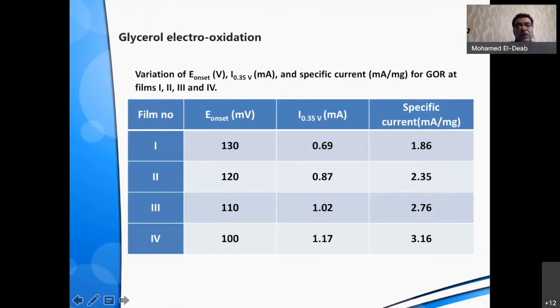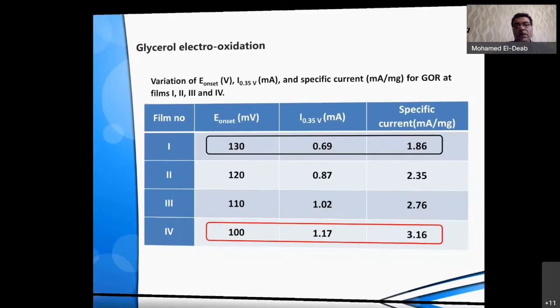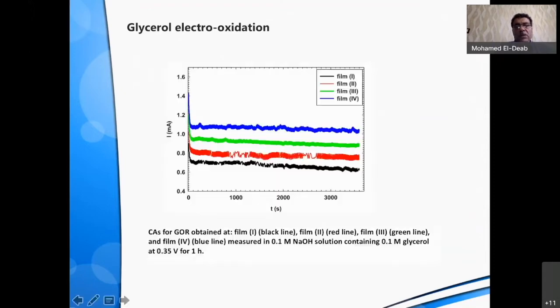So for glycerol electrooxidation, we here summarized the kinetic parameters or electrochemical parameters. The onset potential is shifted, which is the best one for film number 4, prepared in presence of bromide, as well as the current recorded at 0.35 volt is the highest here, also for the same film. Also the specific current, which is the current divided by unit mass in milligram, is the highest also for film number 4. And here this stability current-time, also the same film, shows the highest current over 1 hour.